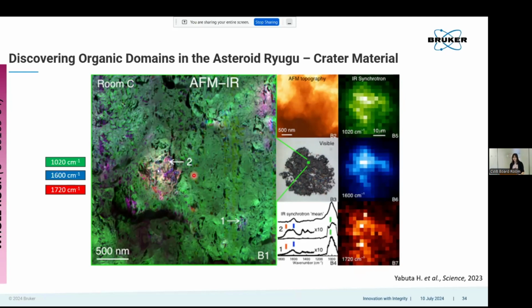So we're going to use the faster, larger scan to then direct the AFM-IR analysis to really dig down deep in. When you do that here, what you see is the distribution of the network of the material, but then you start to see these pockets of organic matter. These are more protected than just being distributed everywhere in the material, which gives us a sense of what is happening when these asteroids would have arrived on Earth millions of years ago, and how the organic materials in the universe might have found their way onto Earth.